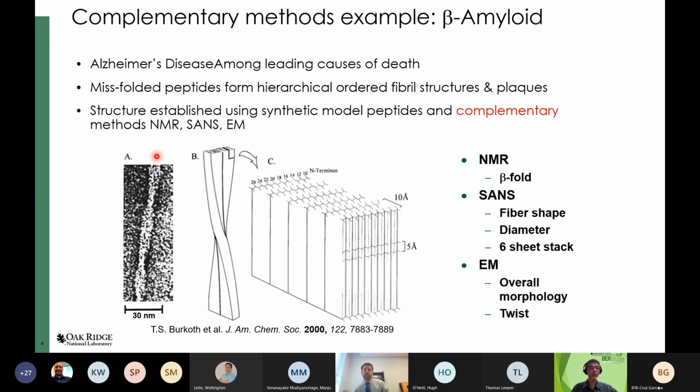And then you can use scattering where you don't see that kind of image, but you can measure some details like how thick is this exactly, or what is the mass per unit length? How many of these sheets do you put together? You can actually measure the weight per length from your scattering experiment that you do not get with that kind of resolution or detail in the microscopy. So that's one way how this can be complementary. There are other examples.